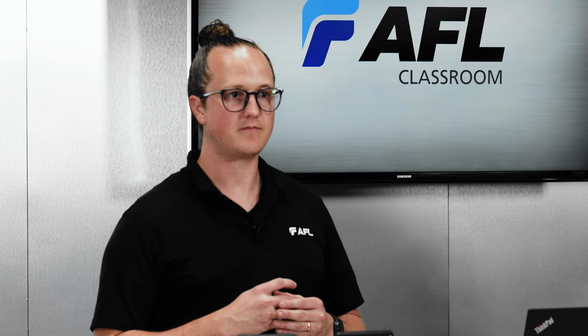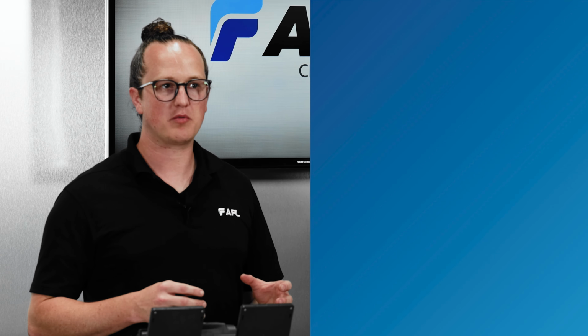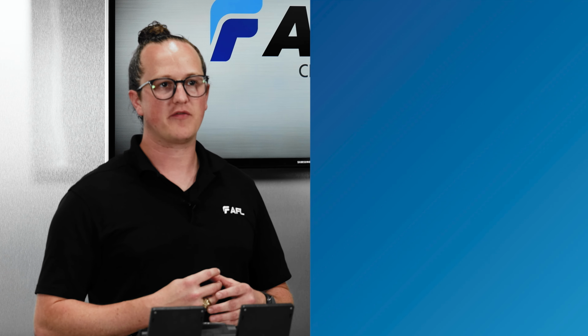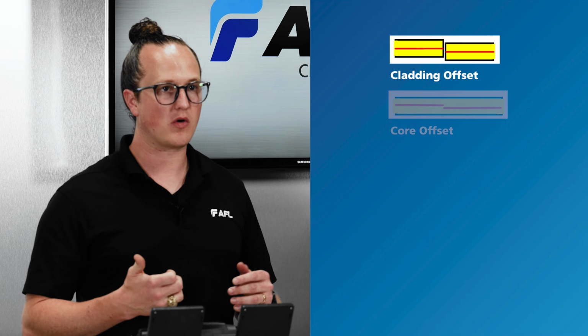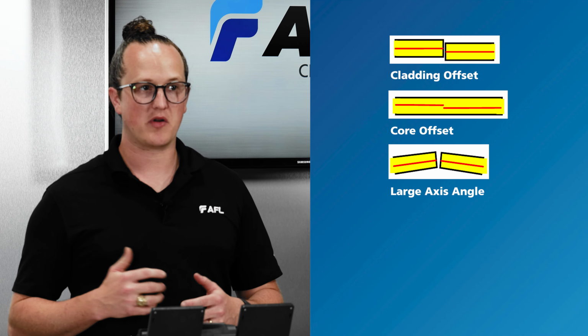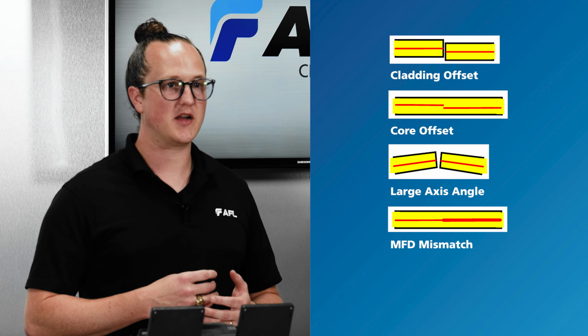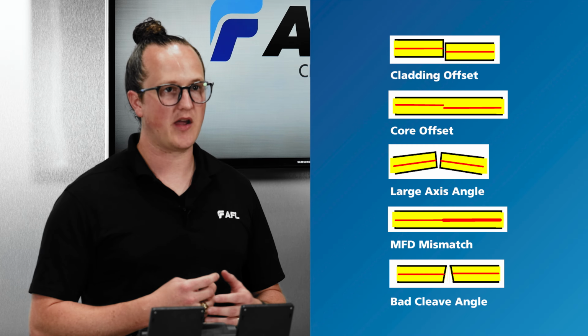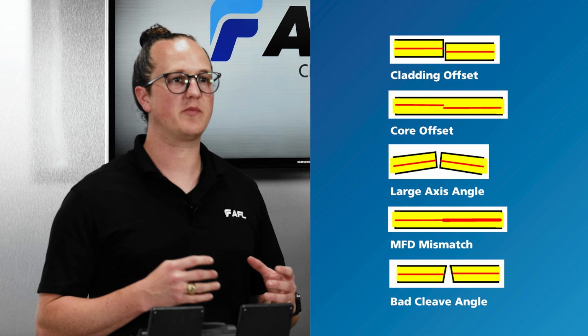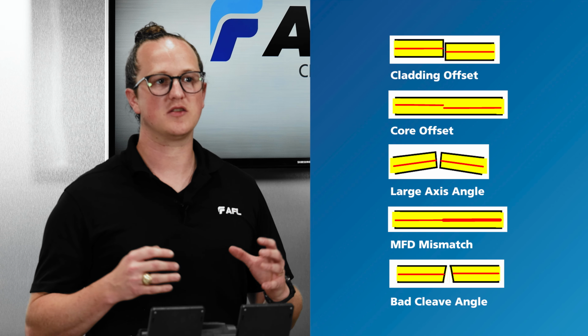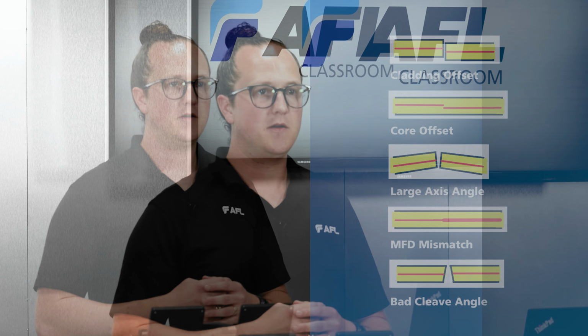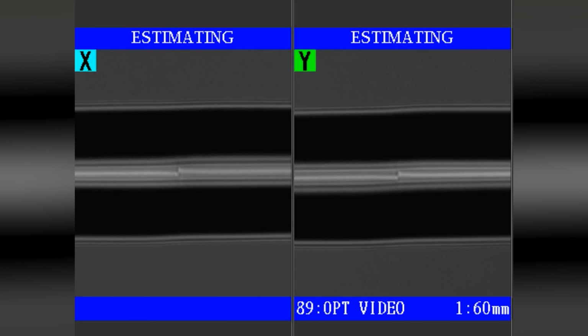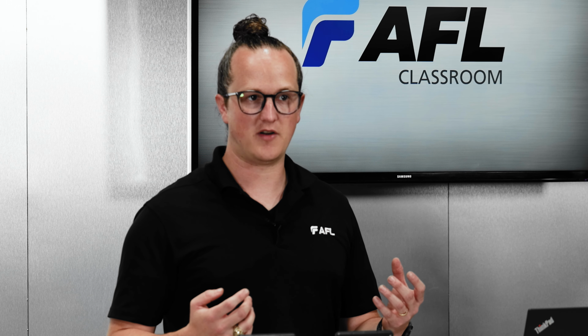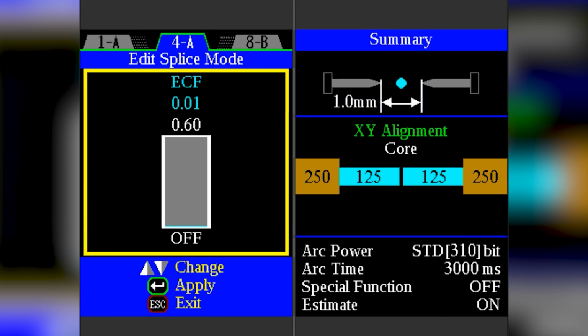during the splice. In the splice images, the main fiber-related conditions commonly observed are from splices with a cladding offset, a core offset, splices with a large axis angle, mode field diameter mismatch, or splices with a large cleave angle. Each one of these has a unique presentation, but on a high level, here are some quick diagnoses for each of these. When fibers are spliced with a cladding offset, usually you'll see some core deformation or core smearing at the splice point. Correct this by experimenting with the eccentricity correction function, or ECF value, to minimize core deformation at